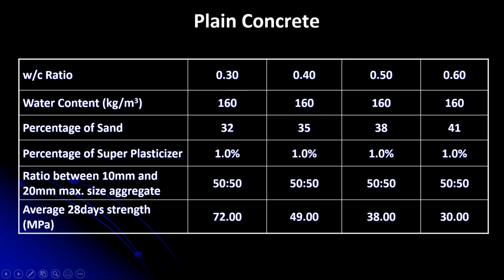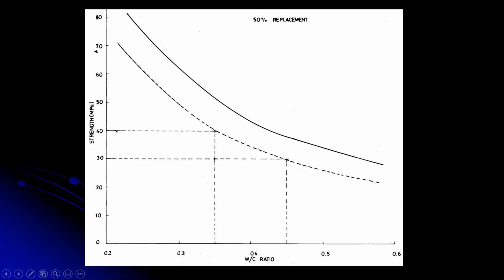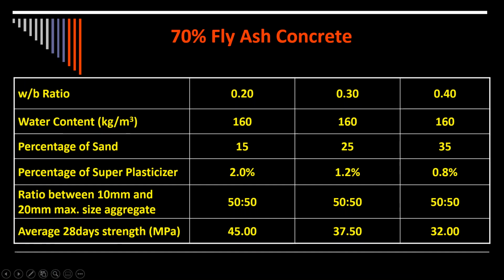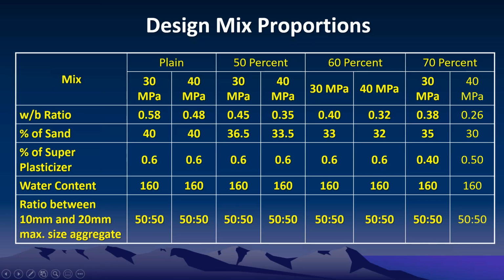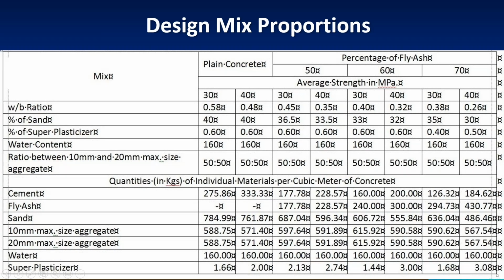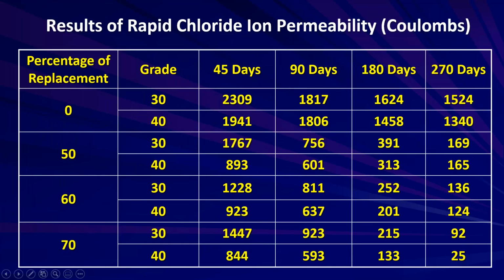The high volume fly ash, of course, it was 50, 60, 70%. I am not going to explain all those things. The only thing is I want to show the coulombs values. Yeah, this is a plain concrete, M30 grade concrete, M40, 50% fly ash and 60, 70, and at different days, 45 days, 90 days, 180 days, and 270.